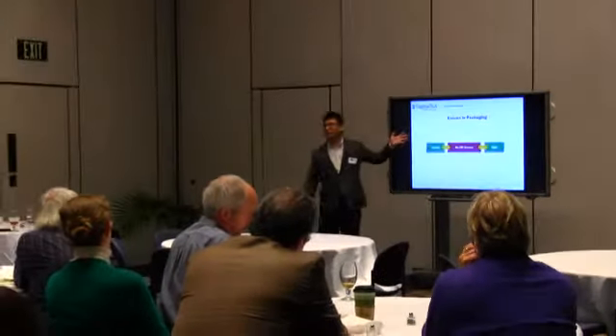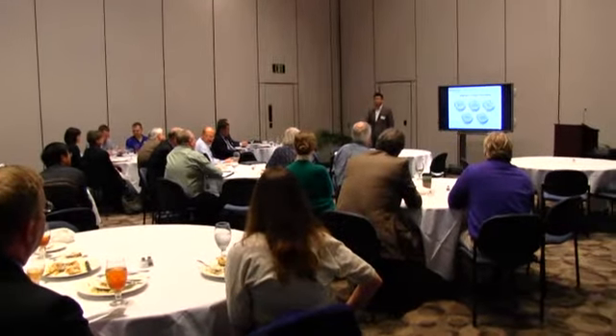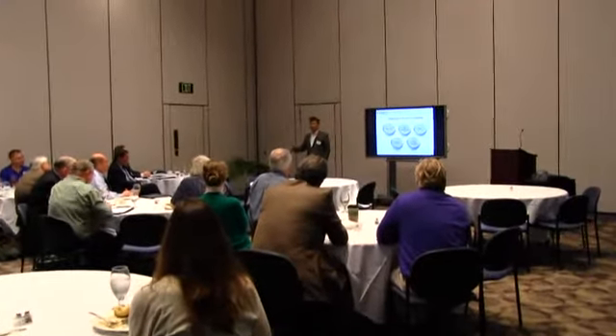We try to use this material for the flexible packaging area and rigid packaging area. These are examples of rigid packaging. It has really good, high HDT. HDT stands for heat deflection or heat deformation temperature. One major drawback of bioplastic like PLA is that it has really low HDT, less than 60 degrees Celsius. The industrial standard for HDT is around 65 degrees Celsius.